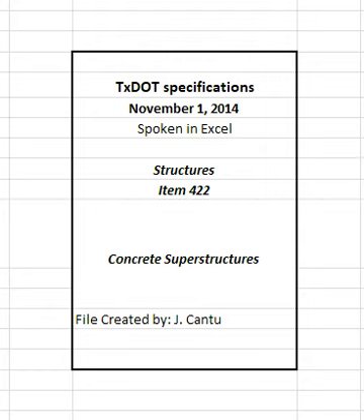Pre-wet the existing concrete by ponding water on the surface for 24 hours before placing subsequent concrete. Use high-pressure water blasting to achieve SSD conditions 15 to 30 minutes before placing the concrete if ponding is not possible. An SSD condition is achieved when the surface remains damp when exposed to sunlight for 15 minutes. Draw forms tight against the existing concrete to avoid mortar loss and offsets at joints.